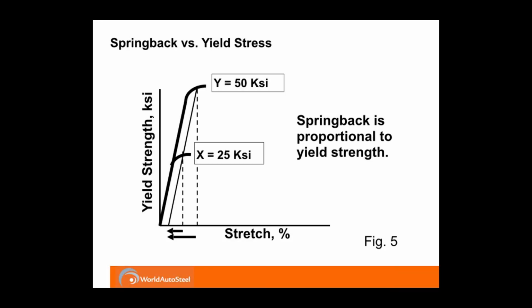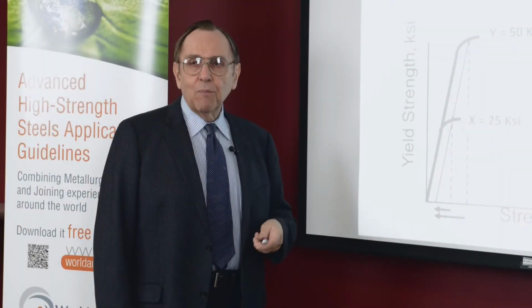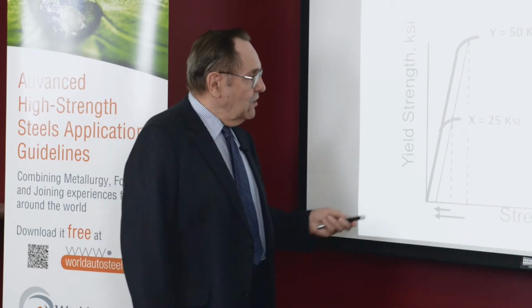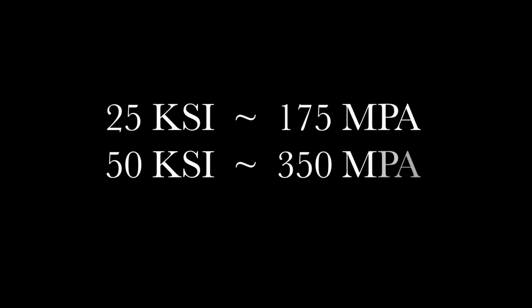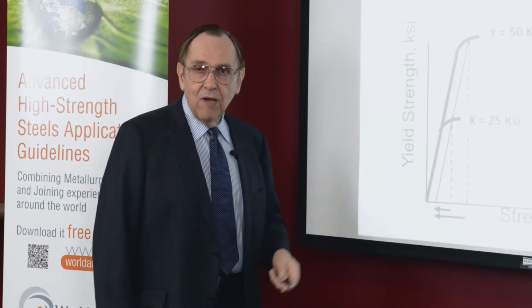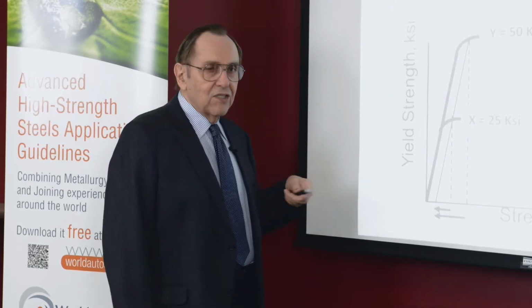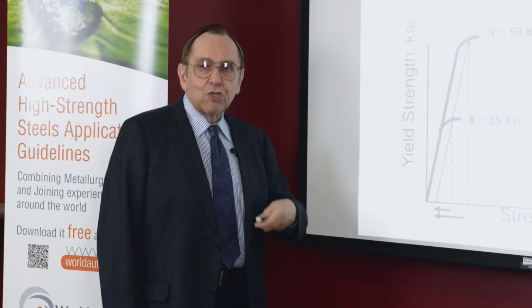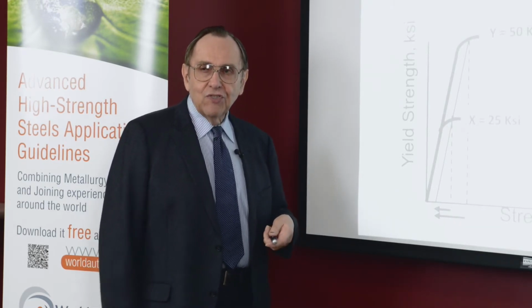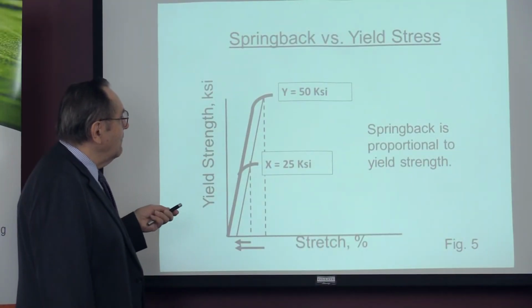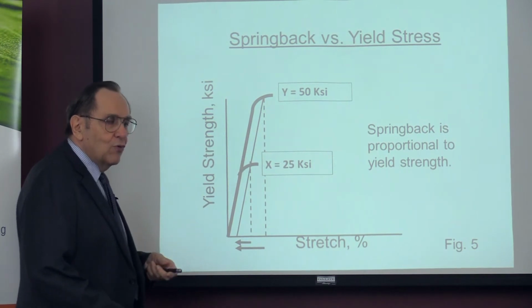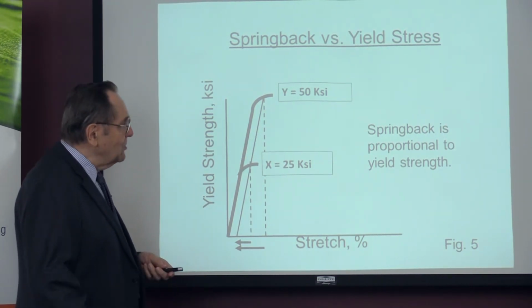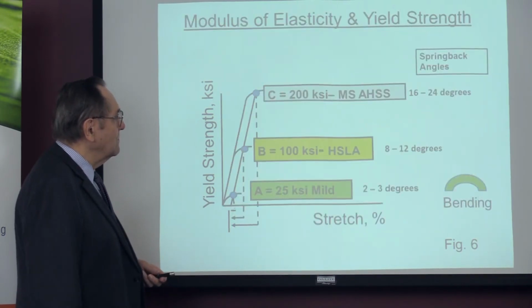Now the Springback, fortunately for us, is proportional to the yield strength. So if we have a yield strength of 25 KSI and we have a certain amount of Springback, we double to a higher strength metal and we come up to 50 KSI, and now we have doubled the amount of Springback. So as the steel gets stronger, Springback increases, your residual stresses are increasing, and you have to pay more attention to how you correct these things and get back to the dimensional specifications that the customer wants.